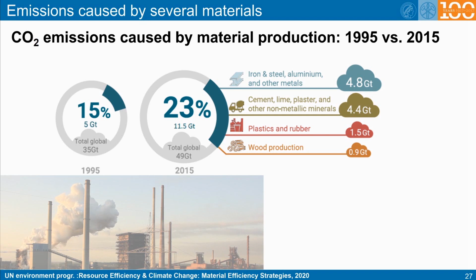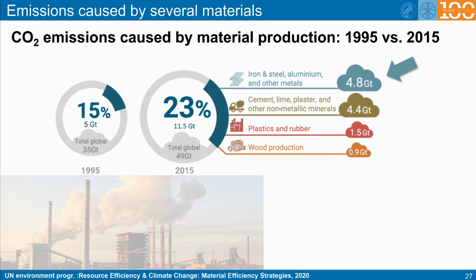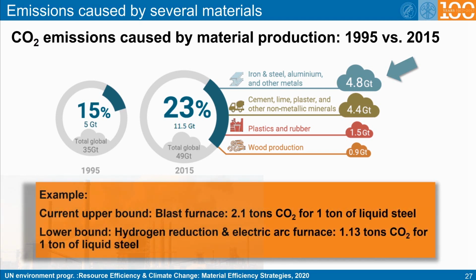Here we see a comparison of the emissions that are caused by several types of materials. It does not only reveal that the metallurgical sector contributes more to the CO2 emissions than the other material classes, but it also shows the enormous increase in the emissions between 1995 and 2015. As a take-home message, it can be memorized here that the current CO2 production for making 1 ton of liquid steel is about 2.1 tons. This number holds true for the current production via the blast furnace and the conventional steel plant route.